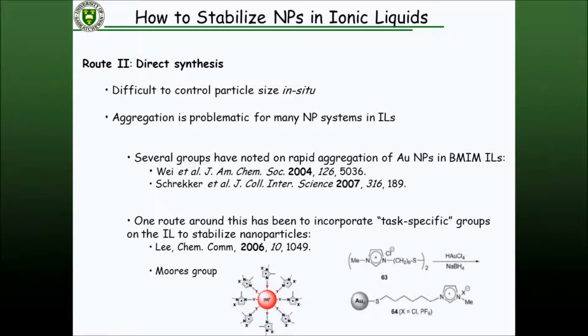We had issues trying to make stable systems, and we found that over time, you make gold nanoparticles, you get a nice, beautiful red solution. You come back the next day, and you've got a precipitate in the bottom of your flask. So they weren't doing very well at dispersing the gold systems, even though others had noticed this. There were routes around that. Audrey Moores at McGill, for example, is one person who's doing that.